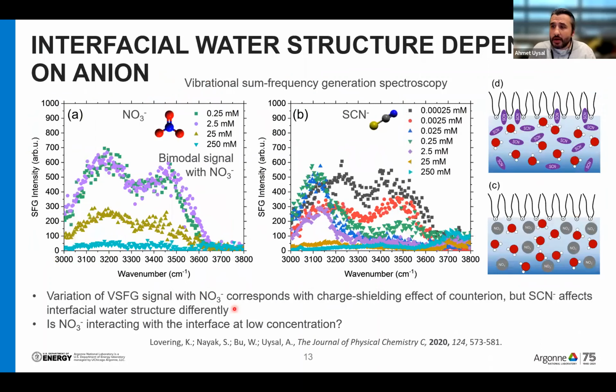As I said, we are now trying to understand these processes and looking at interfaces, what might be the role of the interface, what kind of connections we can get with the organic phase structures and the interfacial structures. One thing we can do is to design a model experiment. We put some model surfactants at the air-water interface, and we change the nitrate or thiocyanate concentration in the bulk, and we study this interface with various methods, including sum frequency generation spectroscopy, X-ray reflectivity, grazing incidence X-ray diffraction. And here I show some sum frequency generation spectroscopy data.